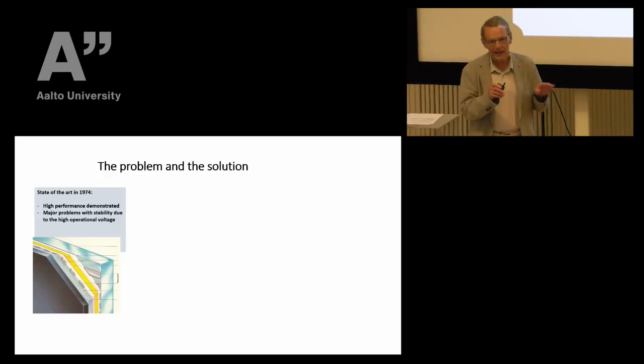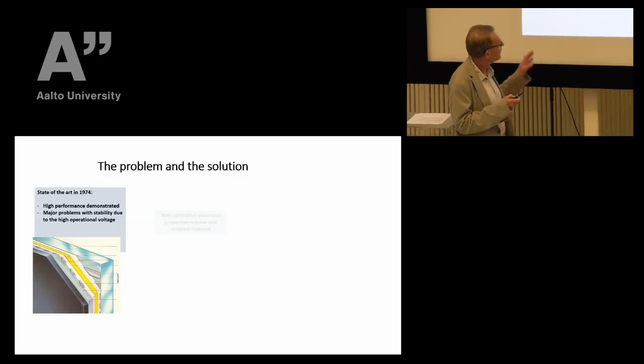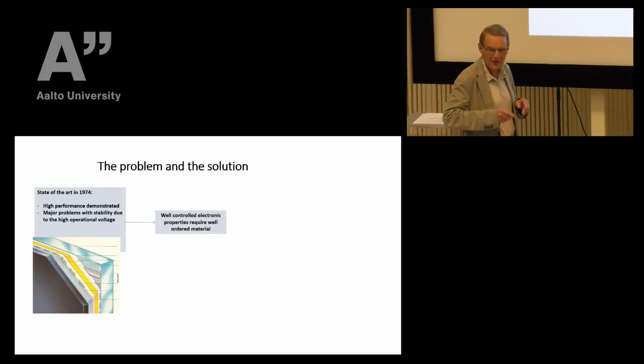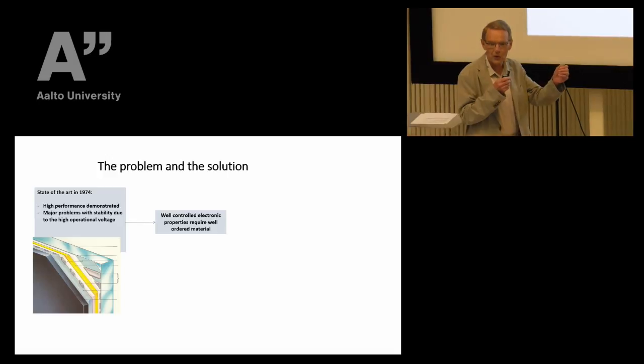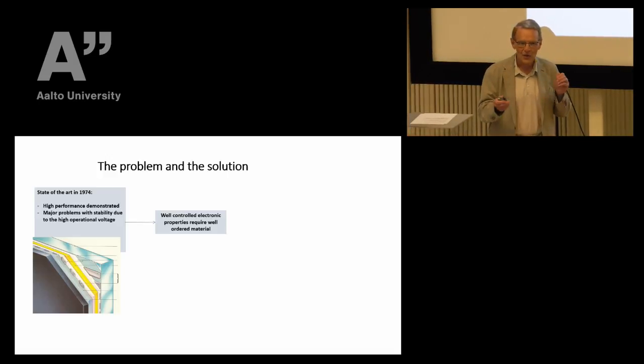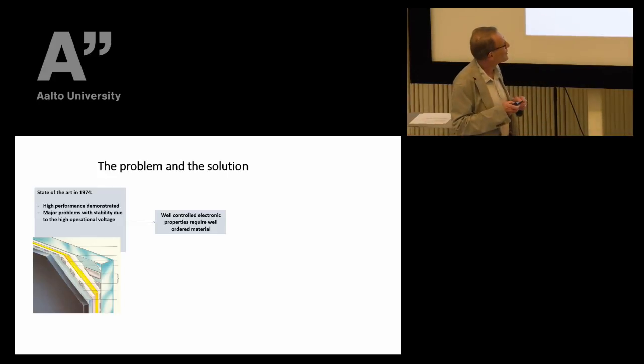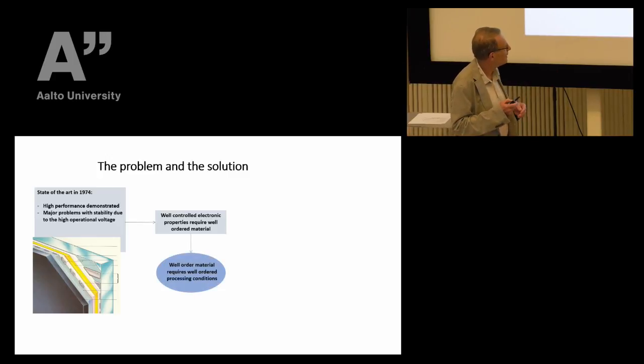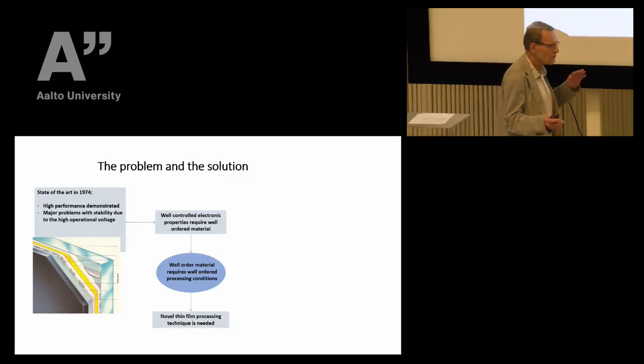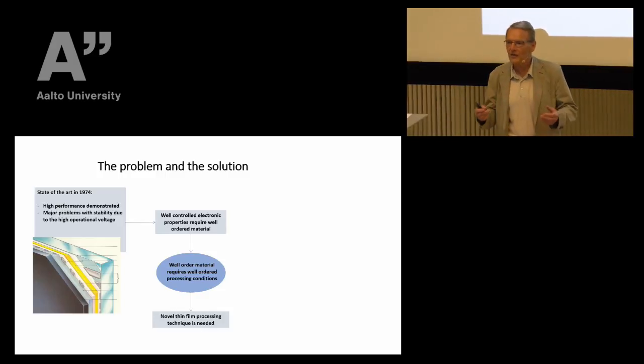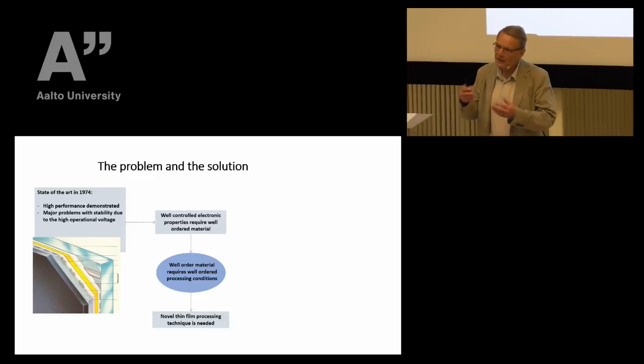Okay, and then how ALE itself was born. Based on the experience, it was nice to have the introduction on the amorphous films, because one of the findings there, I was very disappointed that we couldn't make a practical component, a commercial picosecond switch, with that technology. But I understood that well-controlled electronic properties require well-ordered material. Also, having worked with vacuum evaporation, sputtering and things like that, I understood that well-ordered material requires well-ordered processing conditions.